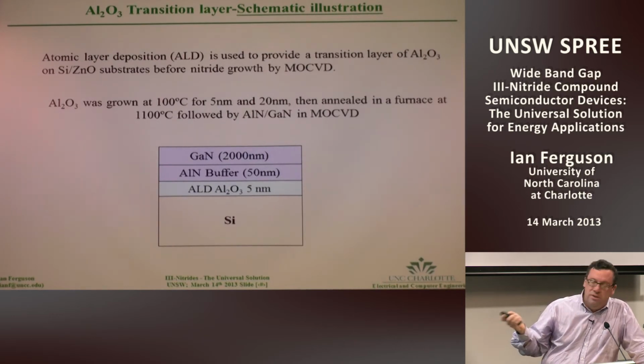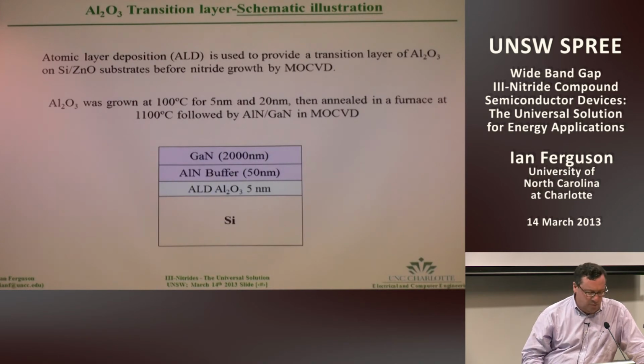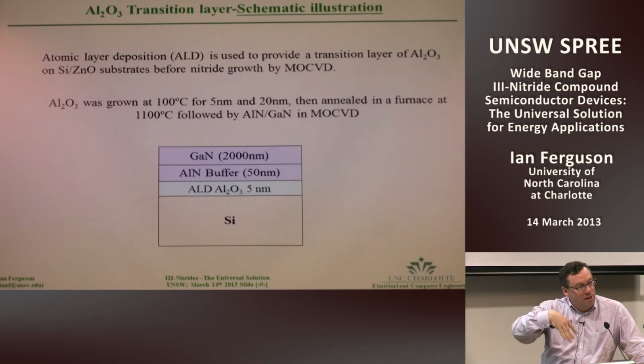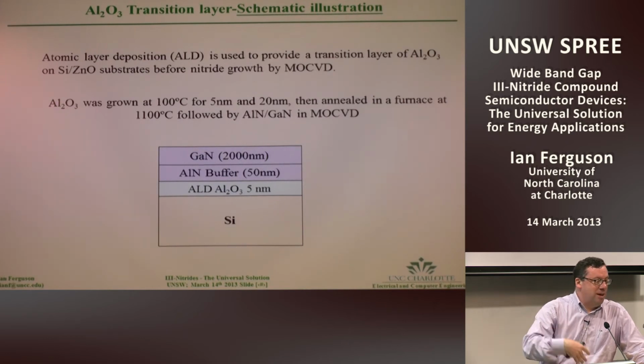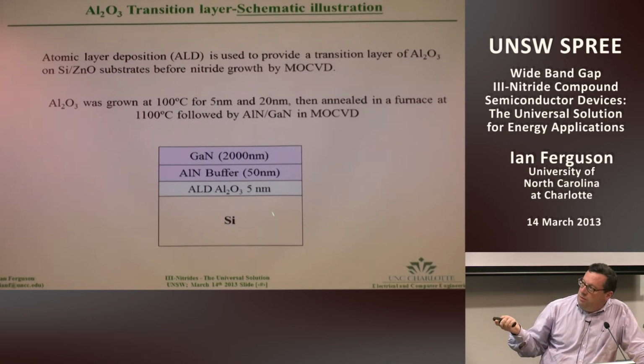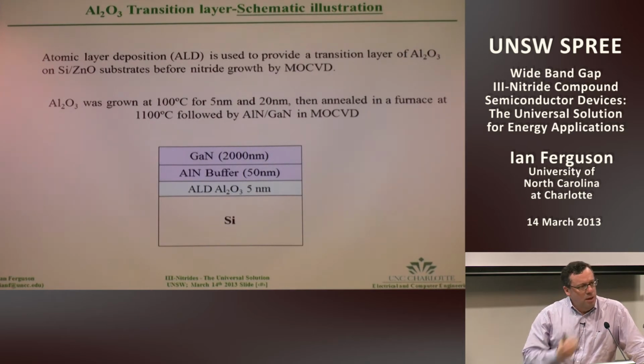So we started developing techniques for looking at other substrate technologies such as zinc oxide for lighting applications. Zinc oxide was problematic because you have an oxide in a nitride environment, a highly reducing environment. So when the students first started growing the samples, they thought they'd lost the samples. In fact, what happened was they dissolved the samples before they could grow on them. And we started developing these interface technologies that we discovered we could use universally in other areas.